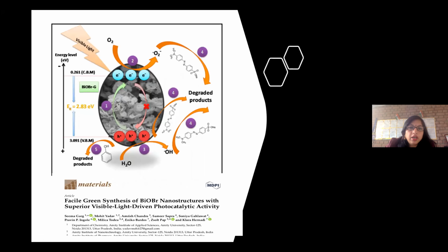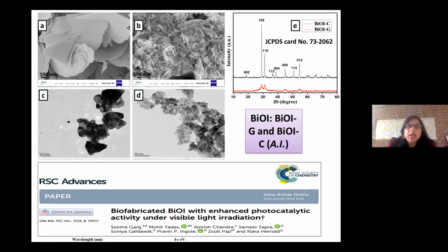It was proved, and this was published in Materials MDPI journal. Now, the thing is BiOI, which has a 1.8 to 1.9 electron volt band gap, has the problem of recombination of electron hole pairs. So BiOI is a good material, but because of the recombination, it does not produce good results when we compare it with these other halides.